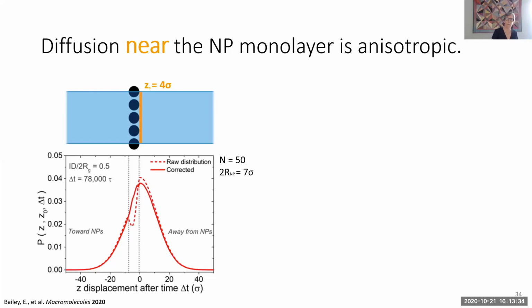And we can do this for the monolayer. So we can look at different Z0 positions, right up against the particles, a little further away from the particles, and a little further still. And we can look at the distribution function, keeping track of whether you're moving towards the particles or away from the particles. The raw data is the dashed curve. And, you know, it's got this weird dip, but that's because we're really close to the nanoparticle monolayer, and diffusing into the particles will be depressed because the particles are taking up a lot of space. But we can correct for that inaccessible volume, we can just calculate that. And then we have the corrected data, which is the solid curve.